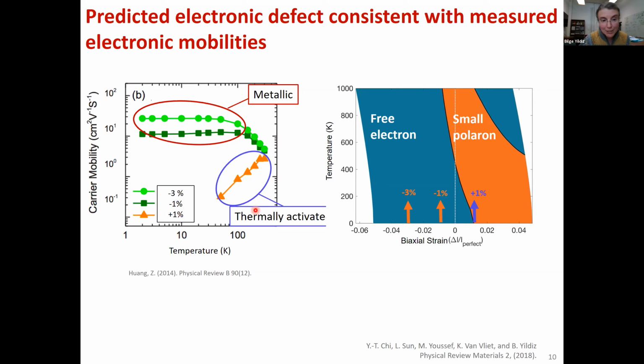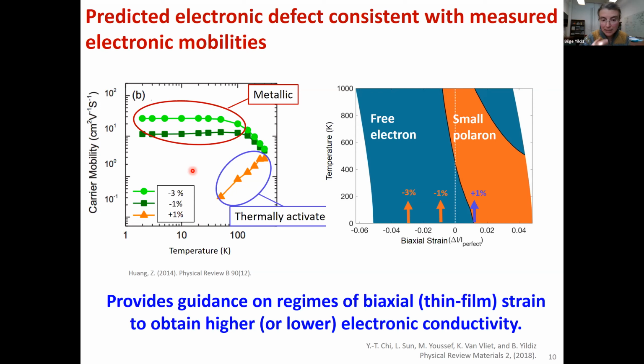So we were quite pleased to see the consistency between our first principles based thermodynamic calculation of different electronic defect stabilities and the experimental behavior of the conductivity that arises from the free electron and small polaron behavior. So having shown this, as I have indicated in the previous slide too, this stability map for the electronic defects gives us some guidance on the regimes of strain versus conductivity.